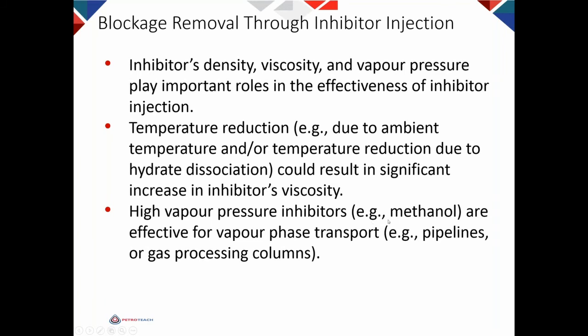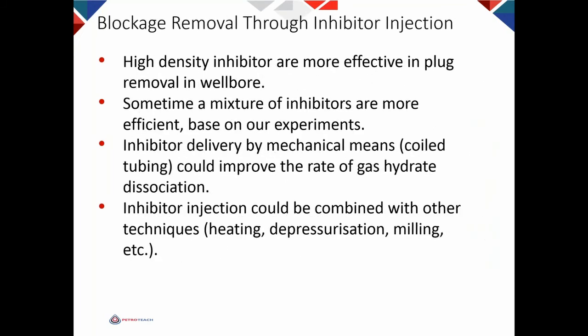Some inhibitors have high vapor pressure, like methanol. They are very effective for vapor phase transport. Therefore, in pipelines or gas processing columns, if you want to remove blockage, they can perform better because the inhibitor can travel to the site of blockage in the vapor phase. But if you have a blockage in a wellbore, then MEG is better because MEG is heavier than water, will always be in contact with hydrate and can melt it. Our experiment shows that it would be more efficient if you use a mixture of methanol and MEG.